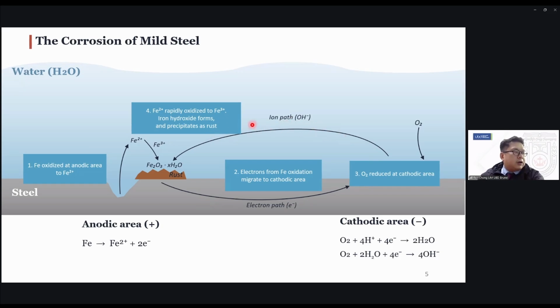The electrolyte is water, so these hydroxide ions travel back to the anodic area and then oxidize the iron, and then you form these iron hydroxides. And these iron hydroxides, if they are not well contained, can actually flake and come off, and this actually leads to material loss.